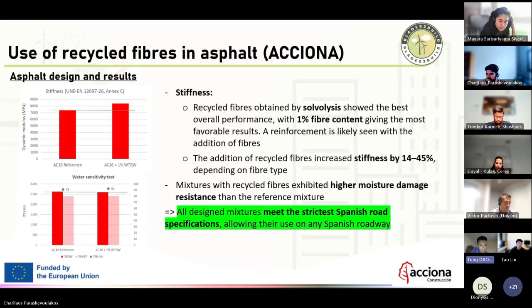I think from 9 to 8 is not so much, it's just within the standard deviation of the tests, but it showed that the durability of the new recipe with the wind turbine blade waste is acceptable and comparable to the ordinary asphalt. So by combining the mixing process, the density, the void content, the stiffness, and the durability, Acciona drew the conclusion that their mixtures meet the strictest Spanish road specifications, allowing their use for any Spanish roadway. So the conclusion is very clear and very impactful in the way that the recipes are ready to be used if there is any opportunity where the asphalt will be used for new pavement, they are ready to propose this.